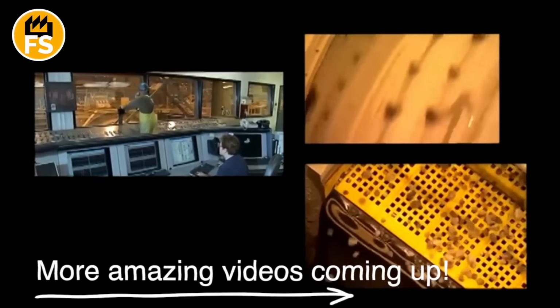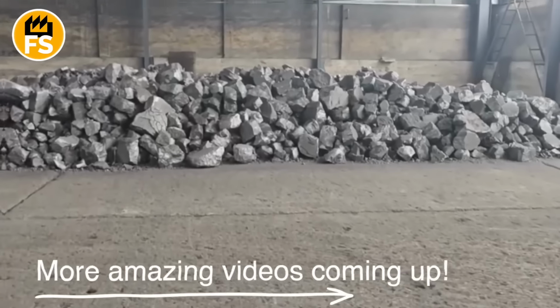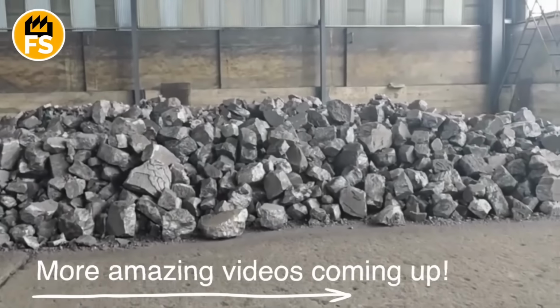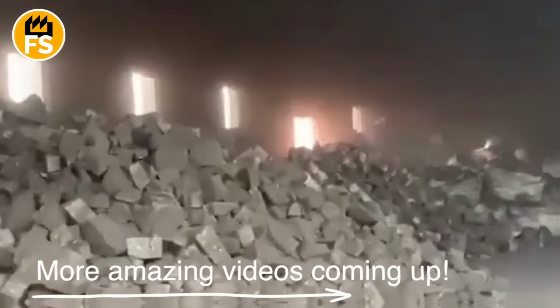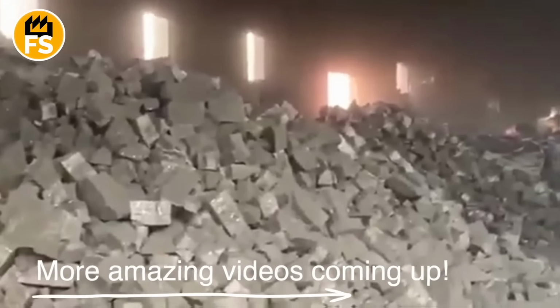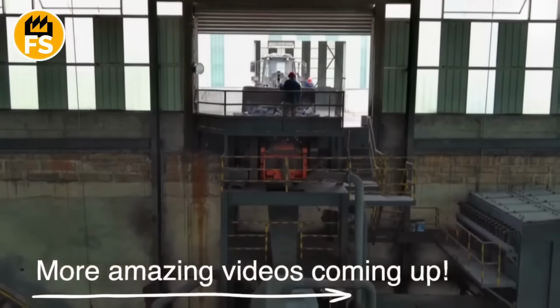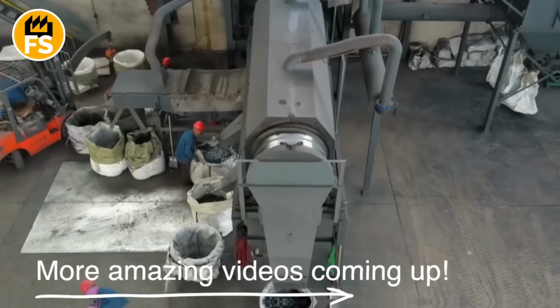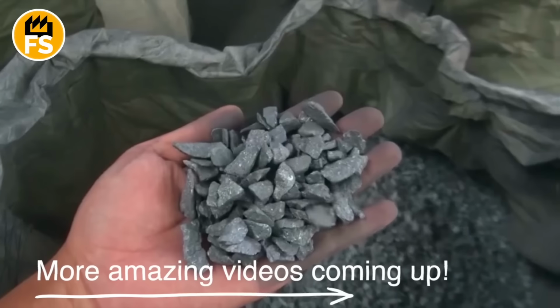An arc from graphite electrodes melts the charge. Ferromolybdenum is added in portions through a hatch. Oxygen is blown through for refining. Gases are vented. Molybdenum makes steel uniform, heat-resistant, corrosion-resistant, and resistant to overheating. No cracks under pressure. The molten metal is poured into a crystallizer, where finished steel comes out.